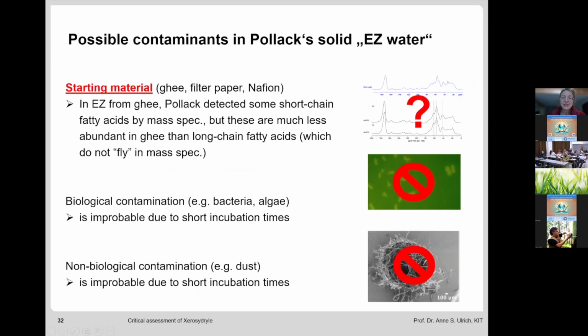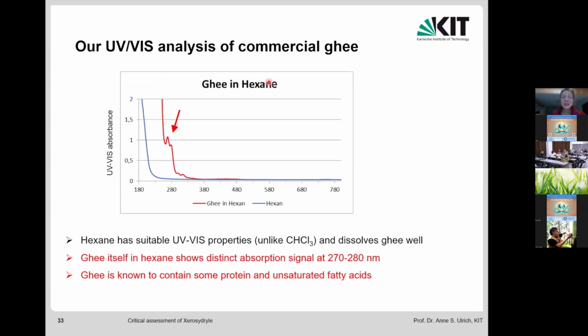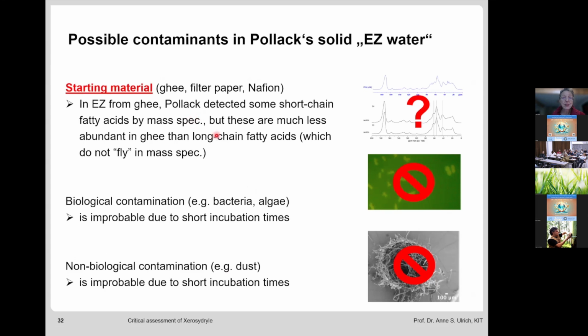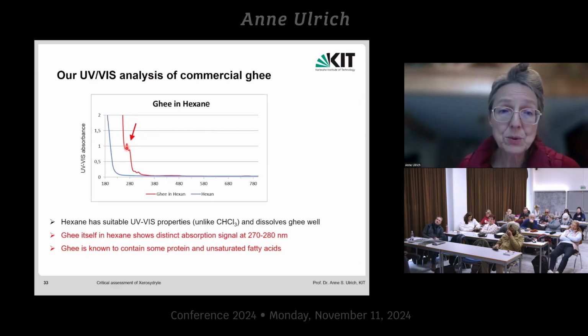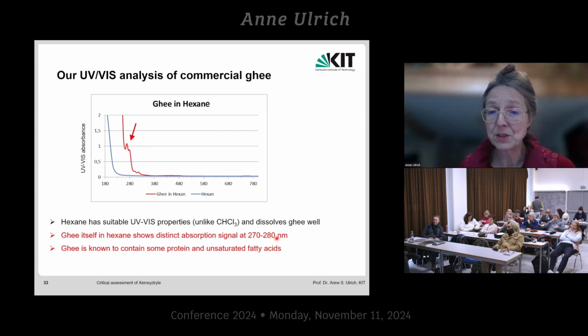The biological contamination is improbable due to the short incubation times, and the non-biological contamination of dust is also unlikely because they had only 10 minutes before they collected their samples. But what about the starting material? This starting material in the Pollack paper was ghee, which is clarified butter. They also used Whatman filter paper, and as a third starting material, they used Nafion sheets. So let's see carefully if we can find anything in ghee that has the characteristic fingerprint signature of 270 nanometers. This is what Jerry Pollack used to show that there is EZ water, because EZ water is supposed to have the fingerprint here at 270, 280 nanometers.